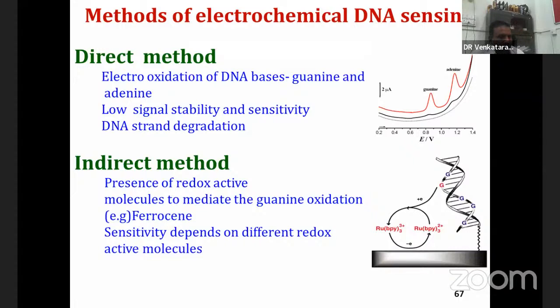So along with the double helical, I also took a metal complex which undergoes direct reaction at the sensor surface. Because this guanine undergoes oxidation and reduction, this oxidation current is received by this metal complex, which generates the signal on the sensor surface. This means if it is not able to undergo oxidation, then this reaction will be prevented. That means if you have a single strand in which the guanine is misplaced, then this reaction will be prevented.